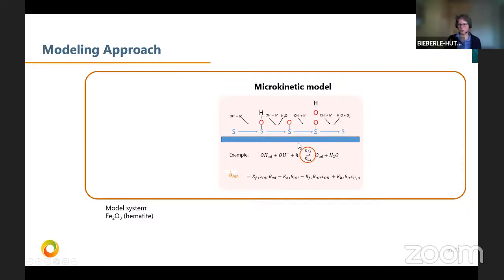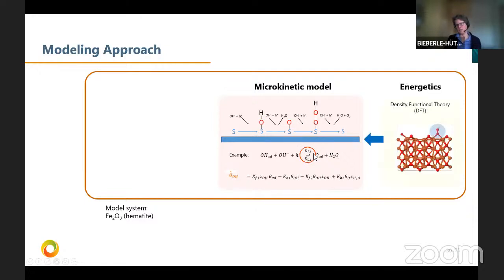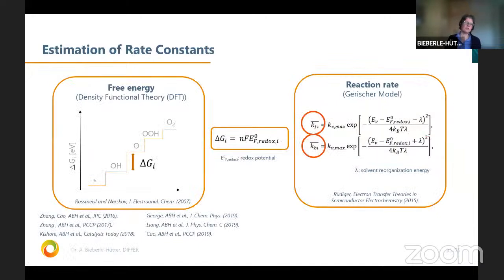We can write down all the different equations for each step and the mass balances. And for the simulations, we need the rate constants. For this, we use DFT to estimate them. So we do the typical free energy calculations as Rossmeisl has shown. We calculate the free energies of these different steps, and we can then relate the free energy to the redox potential. And by this, with this Gerischer model here, we can estimate the rate constants.